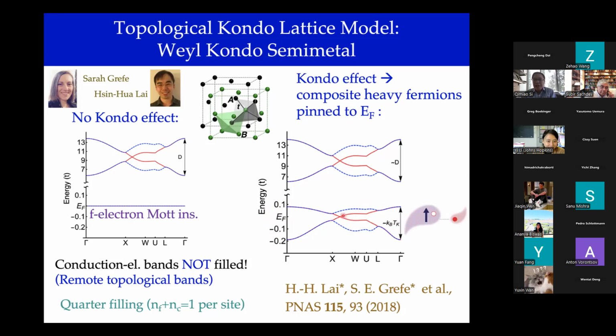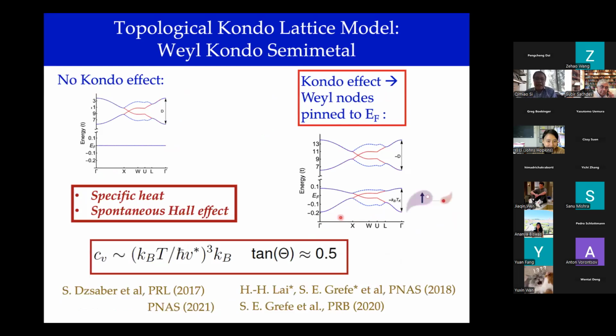For this particular commensurate filling, the system naively would have formed a Kondo insulator, but again, symmetry prevents the insulating gap from happening, and that in the end ends up with Weyl nodes. So this is still quasiparticles, but symmetry dictates that there's a Weyl node formation, which has fairly extreme consequences. So these nodes, by analogy with, say, Weyl nodes of tantalum arsenide, one would like to probe with ARPES. ARPES does not really have the resolution to see that,